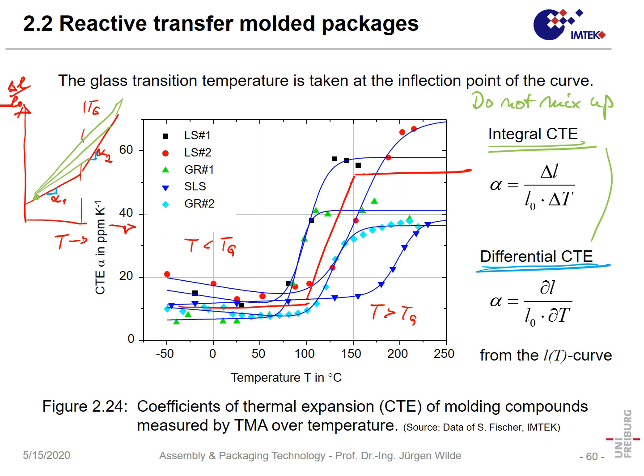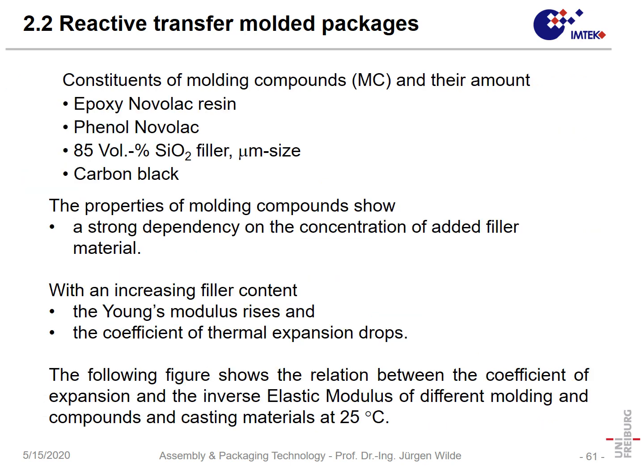Integral and differential CTE. As long as a CTE is not temperature dependent, it doesn't make a difference. So for a metal or for a ceramic, it's not a problem. But in polymers, especially when you exceed the glass transition temperature, there is a big difference. And when you do a simulation, for instance, you can make a large mistake. Yeah? So be aware of this.